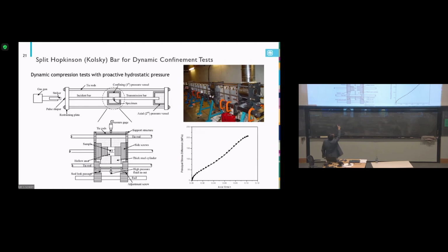So yes, we can develop a pressure vessel. We put the sample in there, apply the hydrostatic pressure, run the Hopkinson bar test, and then we have a stress-strain curve. So that's one approach, which we call the active approach.